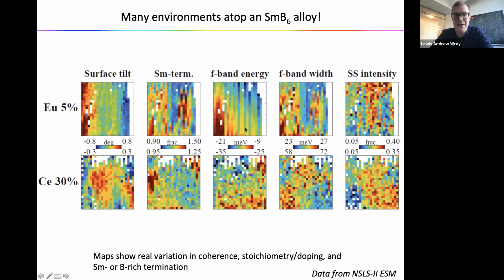You also get a gradient in the sample that represents chemical doping, where you have more electrons on this side, fewer electrons on this side. The cleavage termination can be identified from a so-called multiplet feature in the spectrum. The surface tilt can again be identified. And the intensity of surface states has an interesting correlation with all of this.